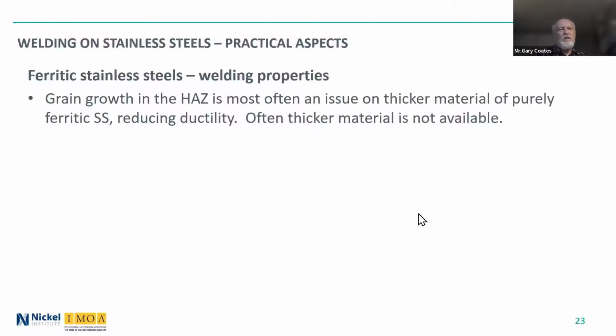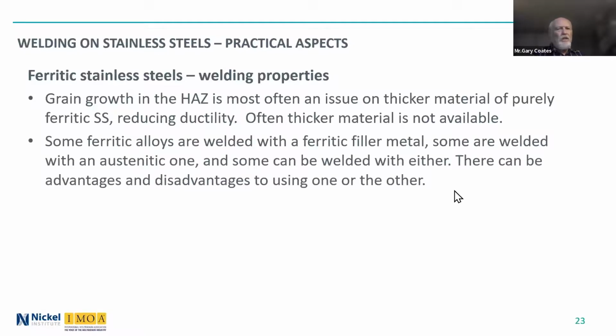Grain growth in the heat affected zone is most often the issue on thicker material of these purely ferritic stainless steels, reducing ductility, and often thicker material is not available because the thicker material from the mill will have a large grain size. So it's very difficult to make some of the pure ferritic stainless steels in thicker material. Some of them are welded with a ferritic filler metal, some are welded with an austenitic one, and some can be welded with either. And there are advantages and disadvantages to using one or the other.